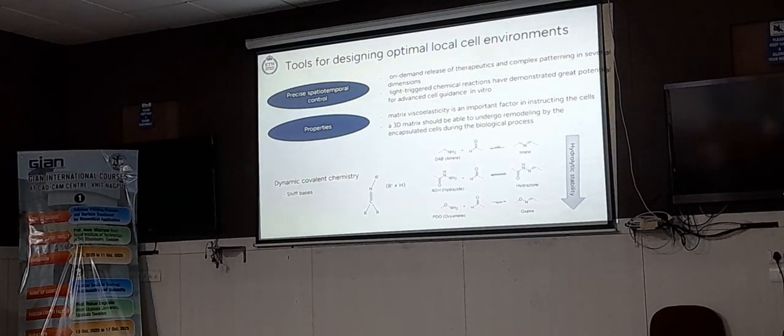And I will be referring to these as TAB, ADH, and PDO, so you know. But the important thing here is to know that there are different equilibriums. So if we react the oxyamine with the aldehyde to obtain the oxime, it is a stable part. So then you have cross-links in the hydrogel. If you have this reaction, then you will have cross-links, the oxime.